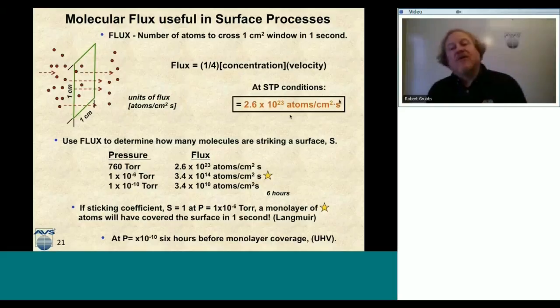Let's take a look at those flux values at different pressures, because we know at lower pressures the flux is going to go down. At 760 torr, we get a flux of 10 to the 23rd atoms per centimeter squared per second. Now at 10 to the minus 6 torr, we get a flux of about 10 to the 14 atoms per centimeter squared per second.